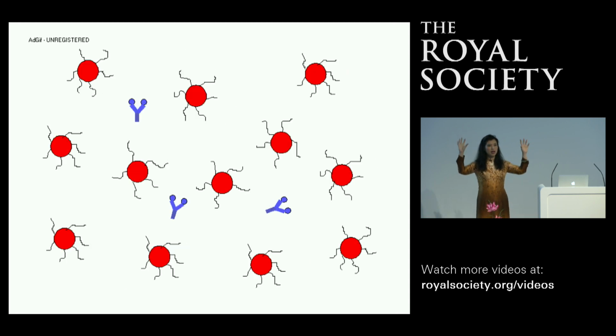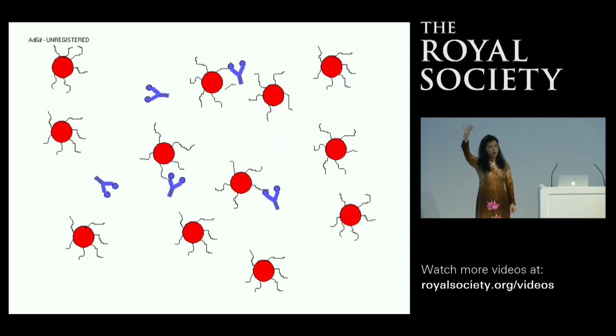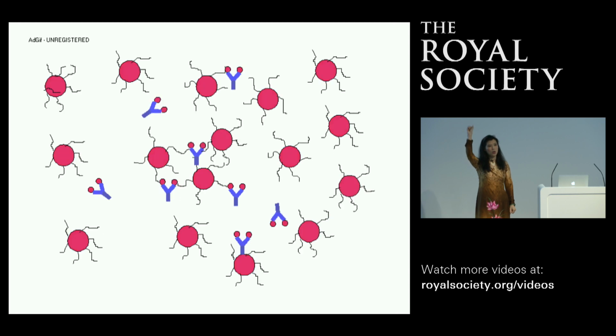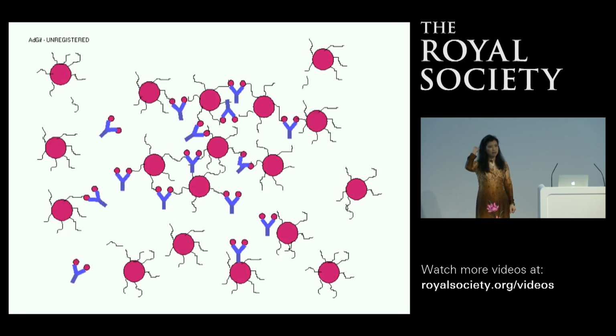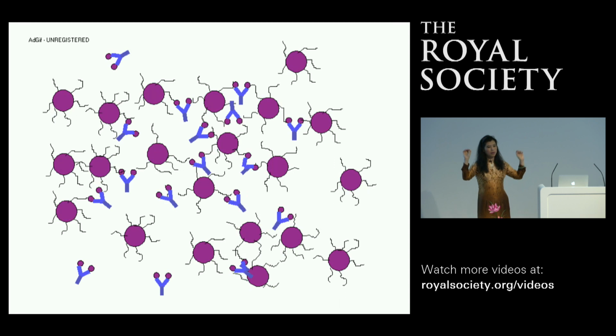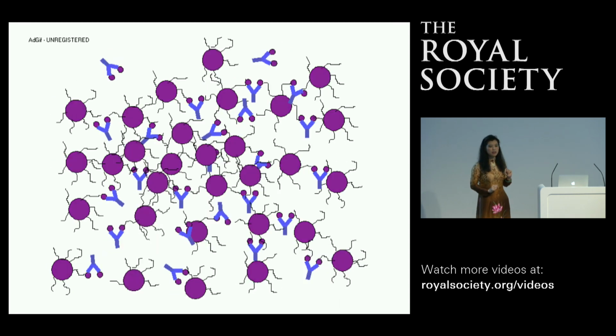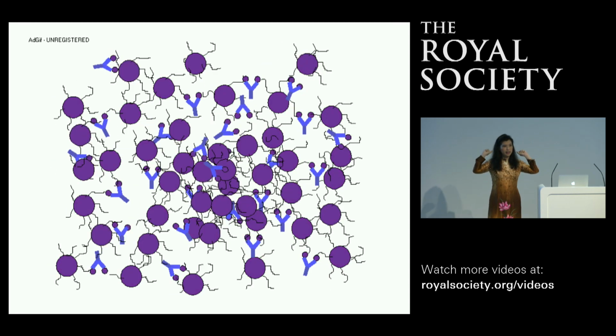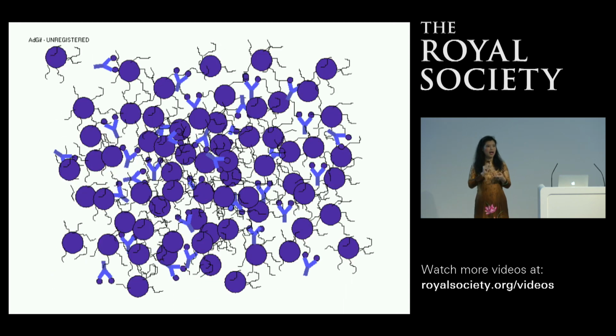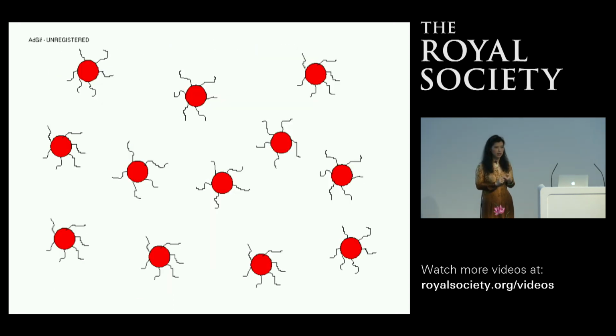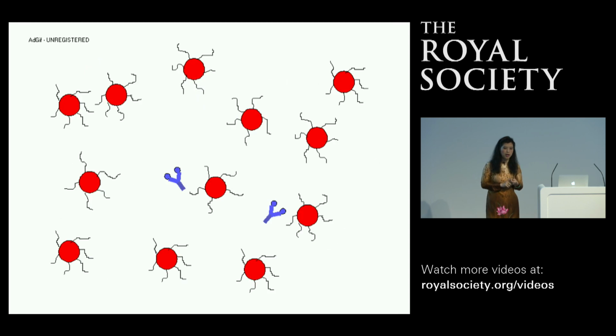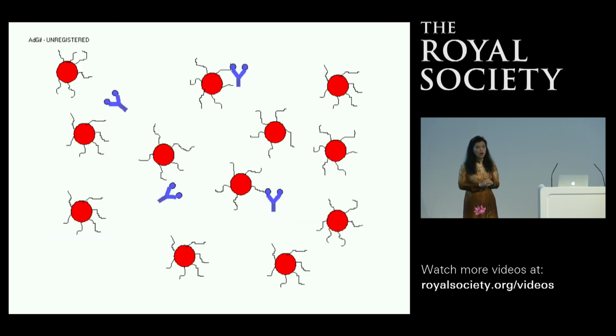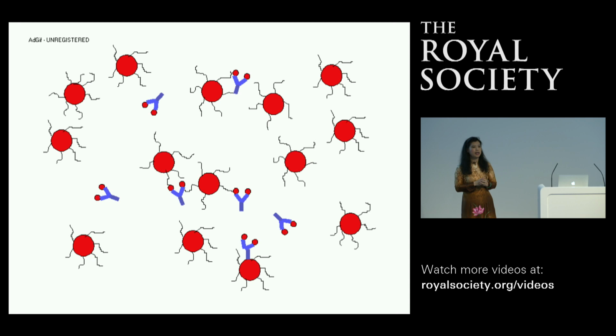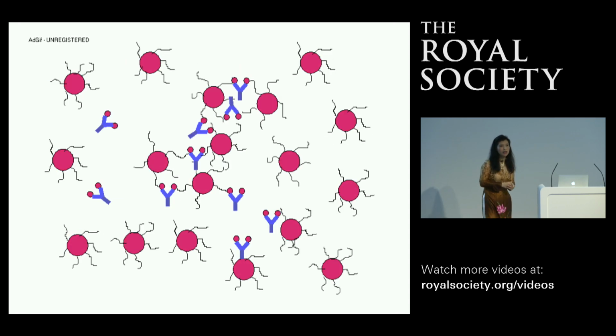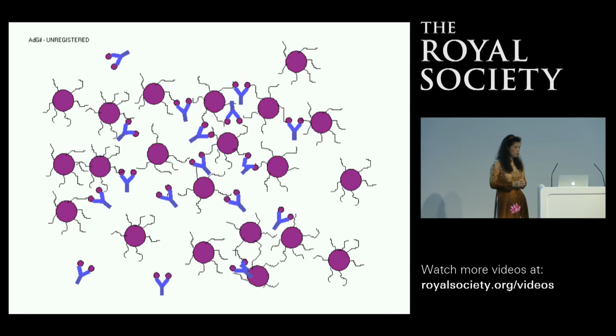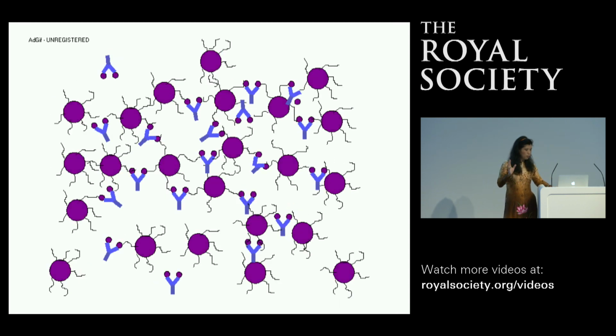So the moment you add antibody with the two binding sites, they're going to grab the particles. It's like a game. If I have only one binding site, I'm only coating my gold particle, and I cannot connect to my neighbor. So the two binding sites are the key. With a monoclonal antibody, you will not see the effect. You need to have a proper antibody. So the more you add, the more aggregation, and you see more effect, and the color changes from red to purple or blue.